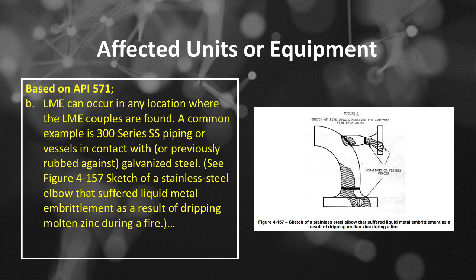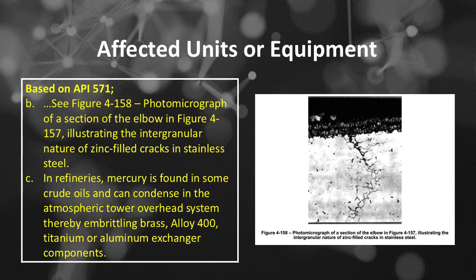See Figure 4-157, sketch of a stainless steel elbow that suffered liquid metal embrittlement as a result of dripping molten zinc during a fire. See Figure 4-158, photomicrograph of a section of the elbow in Figure 4-157, illustrating the intergranular nature of zinc-filled cracks in stainless steel.